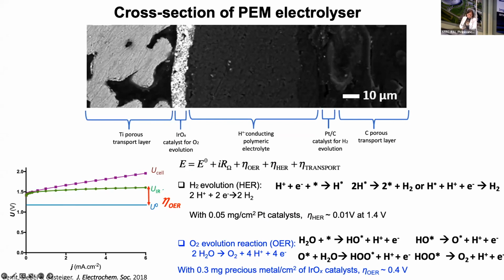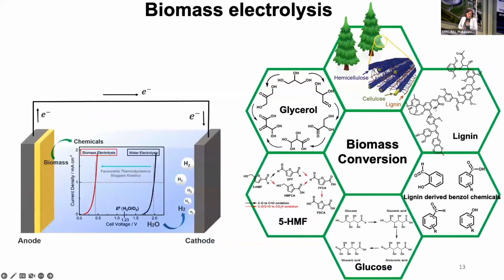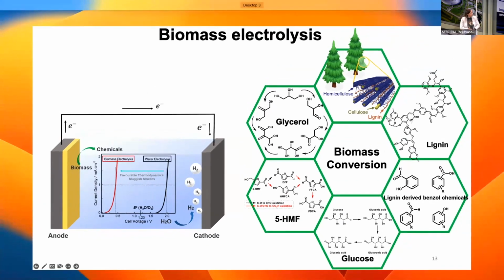So my idea is, instead of electrolyzing water, could we actually electrolyze something else? Biomass offers many opportunities for this because it has protons. The advantage would be that if you oxidize biomass instead of water at the anode here, you would make high-value chemicals while at the same time evolving hydrogen at the cathode. And the nice thing about biomass oxidation is that it happens at much lower potentials than water oxidation. Of course, it will depend on the catalyst and on the precursor, but in principle, you could oxidize this at much lower potentials compared to water. So overall, the efficiency of the whole process would be better. And we have many opportunities for biomass and biomass oxidation.